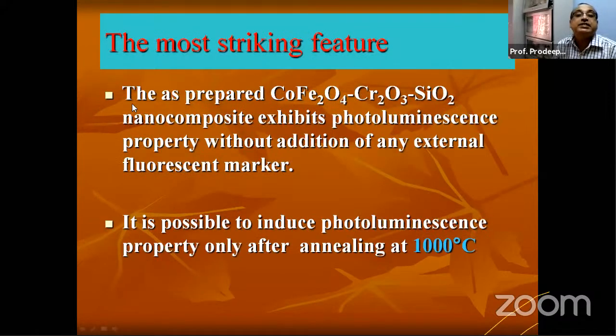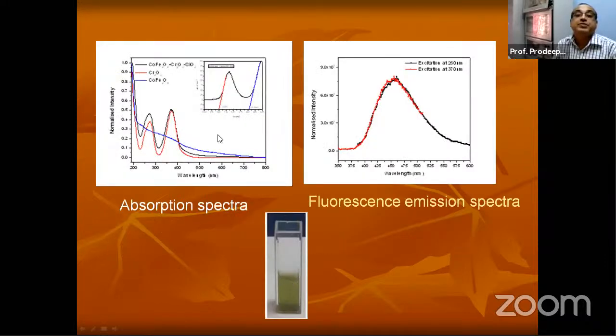Now, here is an interesting thing. The as-prepared cobalt ferrite, chromium oxide magnetic nanocomposite exhibits photoluminescence. Nobody reported such a phenomenon before. It is possible to induce photoluminescence property only after annealing. Actually, we have done some annealing study, and found that after annealing at 1000 degrees centigrade, photoluminescence property is imparted. So this is the absorption spectra, and this is the fluorescence emission spectra.